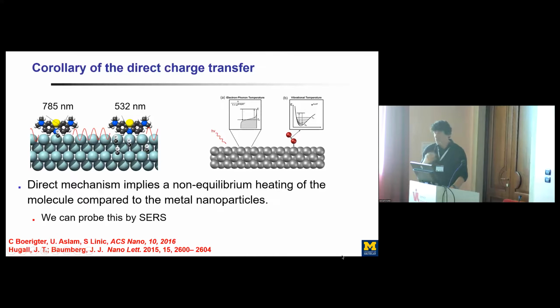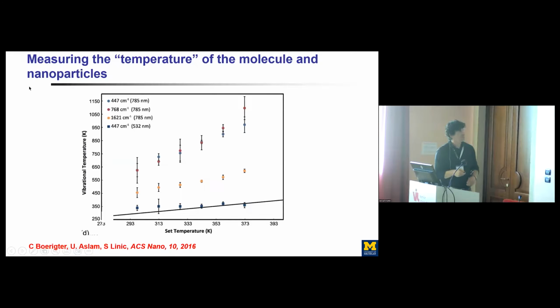So we can actually use this Raman spectroscopy to measure, at the same time, the temperature of the nanoparticle itself by looking at the background of the anti-Stokes signal. So that's what we did here. And again, we are now measuring the temperature of the molecule, and we are measuring the temperature of the nanoparticle for these two lasers. And what we see is, again, that at 532, we have a thermal equilibrium between the nanoparticle and the molecule itself. So basically, the energy is propagating from the nanoparticle to the molecule. Everything is in thermal equilibrium.